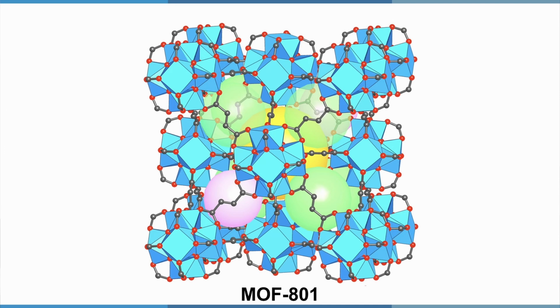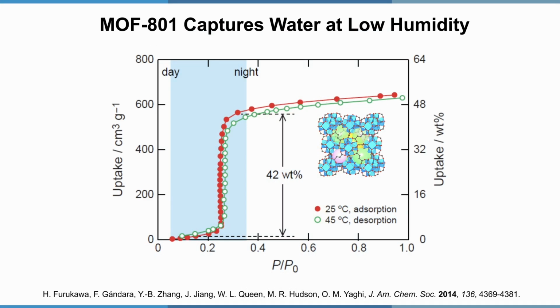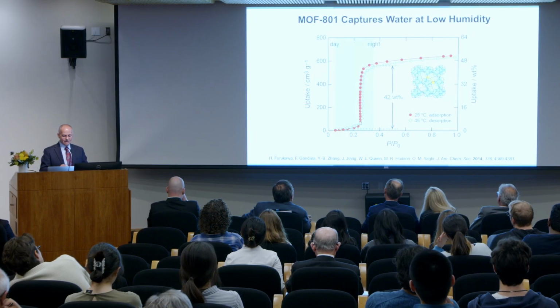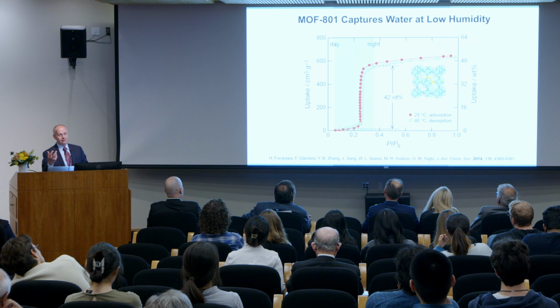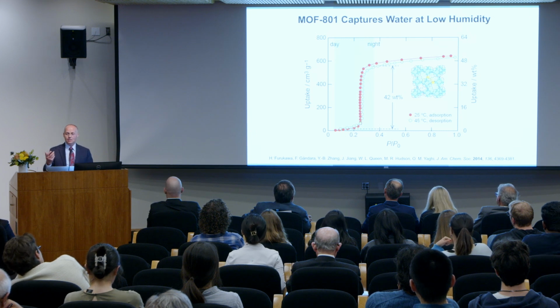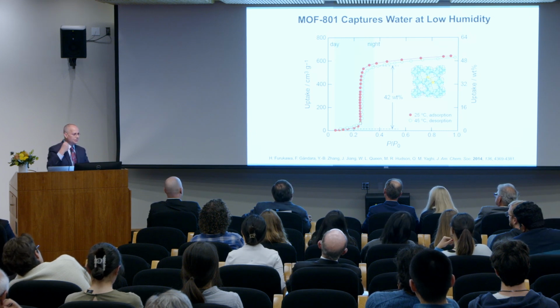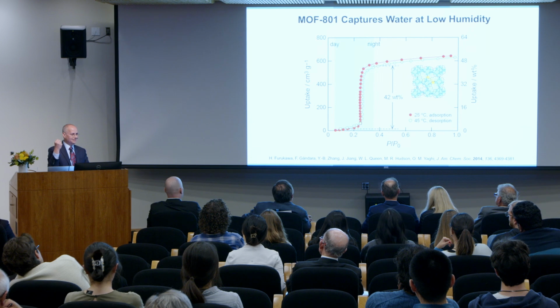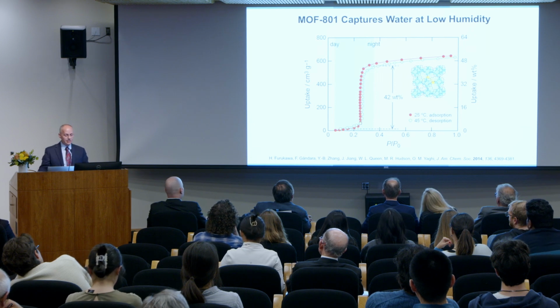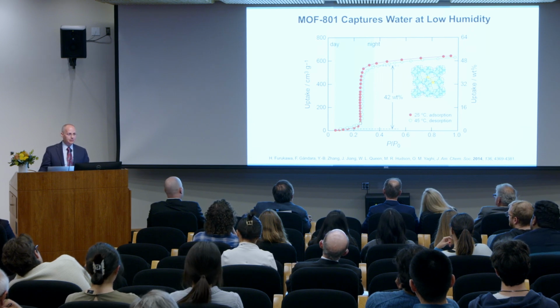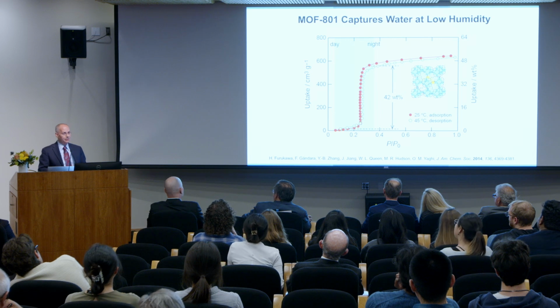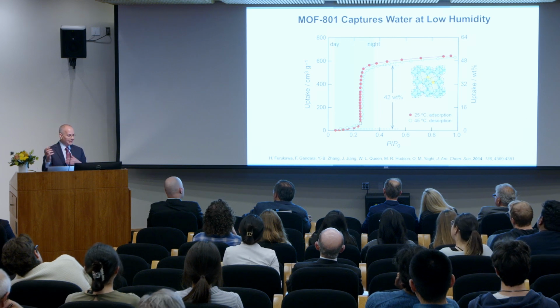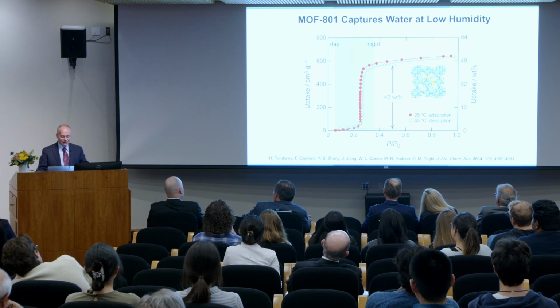So this is a MOF. I won't describe it, but it's a zirconium MOF. And the student came to me with this red plot and said, well, that's the behavior of this material in water. We were studying the behavior of materials in water because we were trying to trap CO2 in the presence of water. And as I showed you yesterday, CO2 capture is helped by water, but we didn't know that at the time. So we were studying how CO2 and water behave.